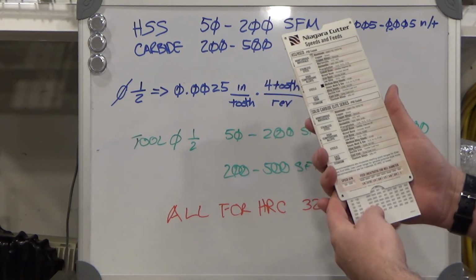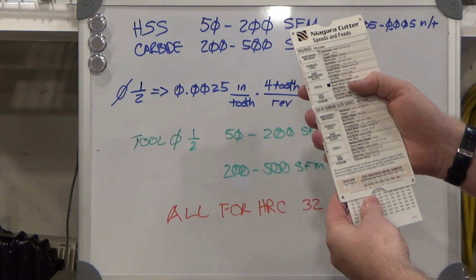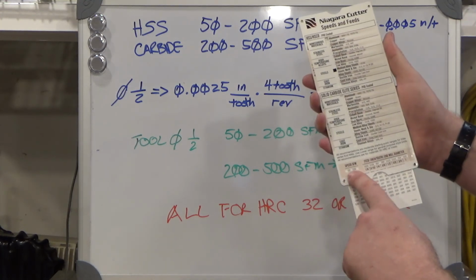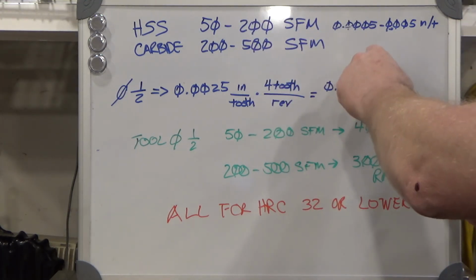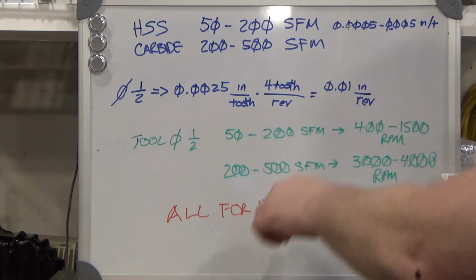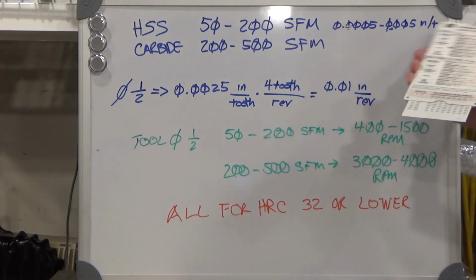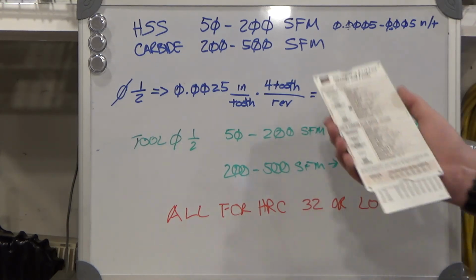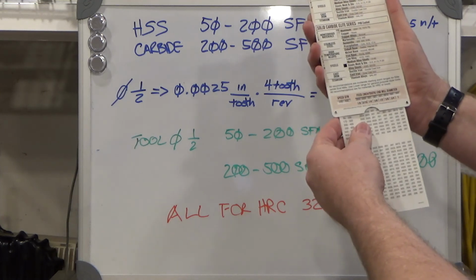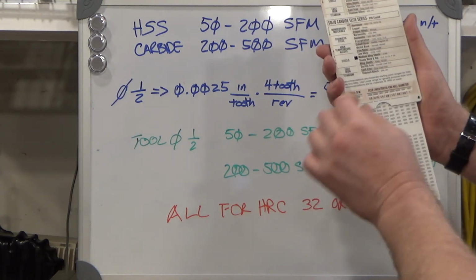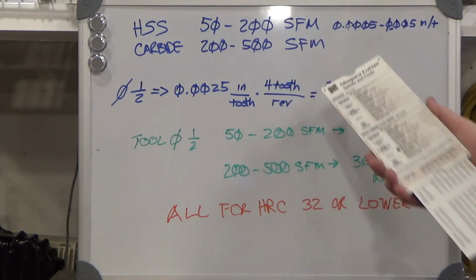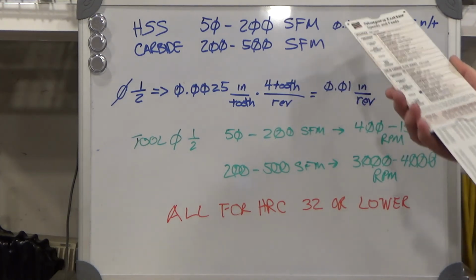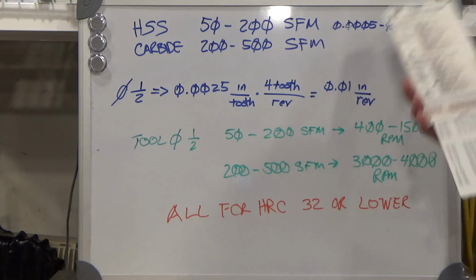So the way this chart works on one side is you pick your alloy. For example, here is medium alloy steel, which includes 4140 for a high-speed steel cutter, and you come down here and it's 50 to 200 surface feet per minute, with half a thousandth to 5 thousandths inches per tooth as a feed rate. For carbide cutters, you just slide down to the bottom section and go back to 4140 and 200 to 500 surface feet per minute with the exact same feed rate, between half a thousandth and 5 thousandths inches per tooth.